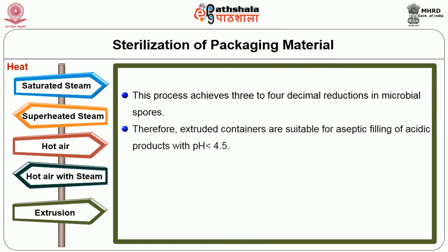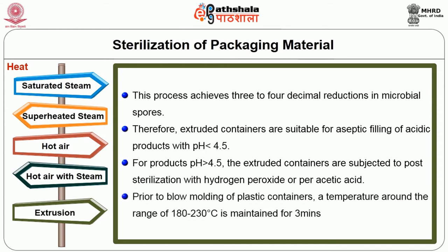The extrusion process achieves 3 to 4 decimal reductions in microbial spores. Therefore extruded containers are suitable for aseptic filling of acidic products with pH less than 4.5. For products with pH greater than 4.5, the extruded containers are subjected to post sterilization with hydrogen peroxide or peracetic acid. Prior to blow molding of plastic containers, a temperature in the range of 180 to 230 degrees Celsius is maintained for 3 minutes.